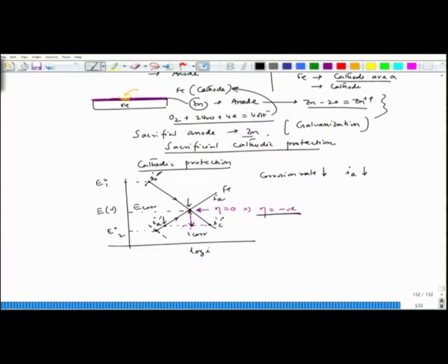Okay. So, it is a decrease in the corrosion rate of iron, and interestingly during that I am sending this extra negative current, and the I applied is nothing but IC minus IA, and here IC is greater than IA.